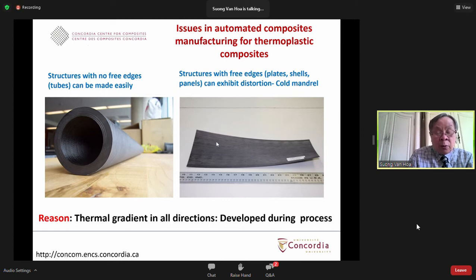Then what we find is that right after the process, you have the distortion, even for the case of a unidirectional layer, when you make a unidirectional layer, okay? Now, the reason for this is because of the thermal gradient, because the temperature varies throughout the space in X, Y, Z direction, in all directions. And this developed during the process. So right after you make it, you also have this kind of situation.